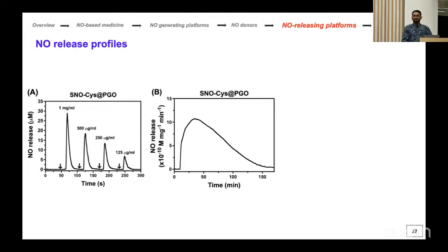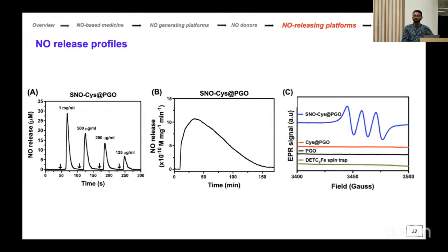There are also many controversies around nitric oxide detection methods. So we also developed a novel protocol using electron paramagnetic resonance, EPR, using a spin trap method, where the spin trap forms an adduct with the nitric oxide and gives you a 3-line spectrum of nitric oxide. We show that the spin trap on its own doesn't have any nitric oxide, and neither does porous graphene oxide or cysteamine-functionalized, but once it's conjugated with SNO, it does.